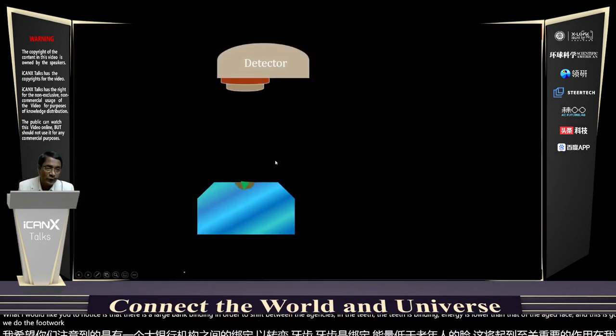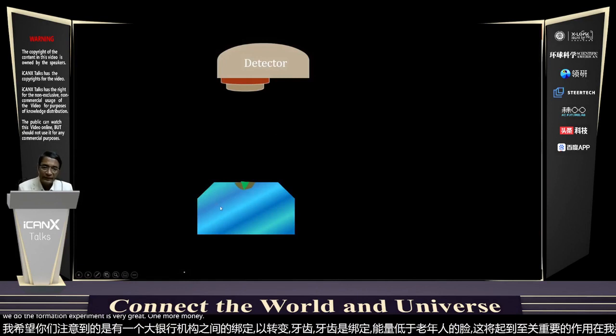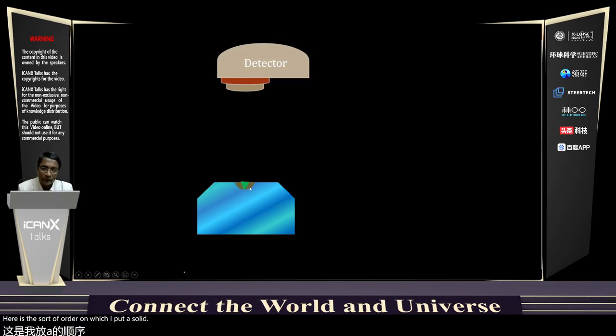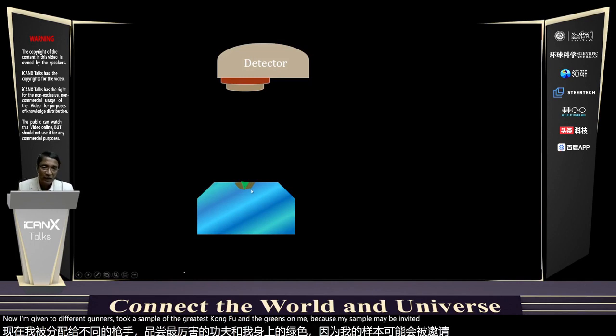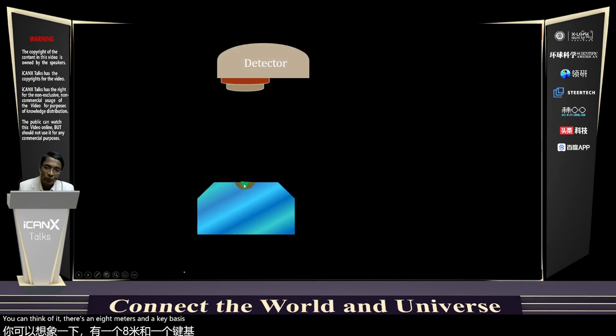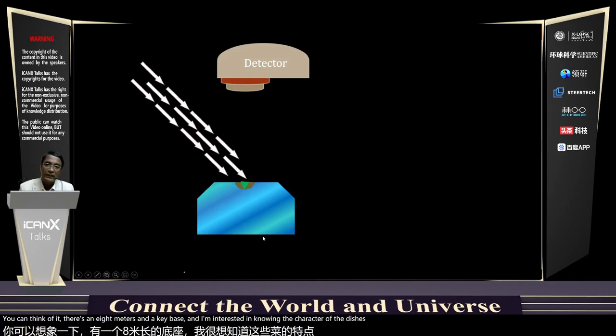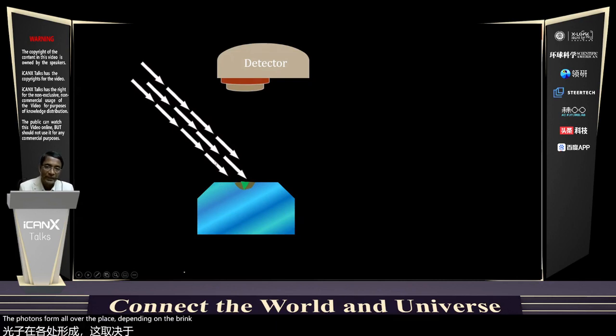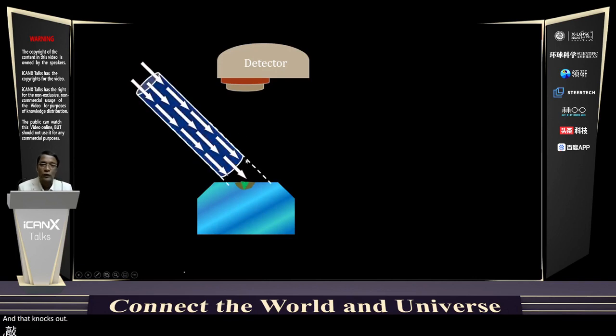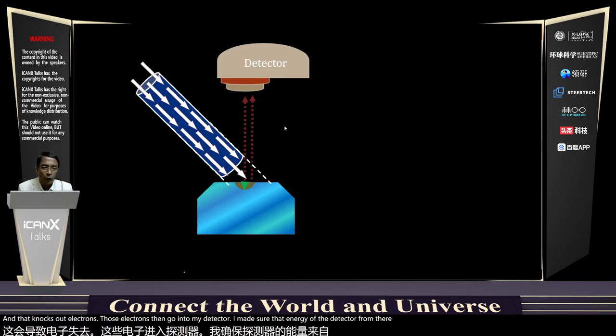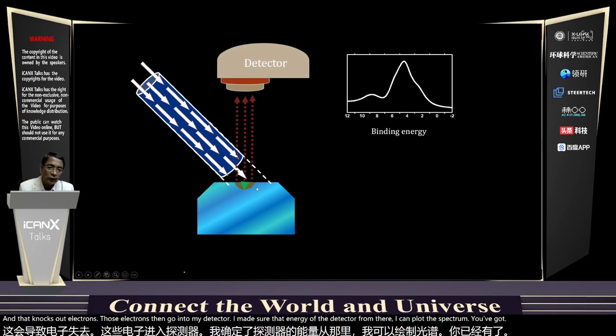How do we do the photoemission experiment? A very quick one. Normally, here is the sample holder on which I've put a sample. Now, I've given two different colors to the sample, the gray sample and the green sample, because my sample may be inhomogeneous. You can think of it, there's an H phase and a T phase, and I'm interested in knowing the character of the T phase. Normally, the way we do the photoemission, we bring in photons. The photons fall all over the place depending on the spread of the beam, and that knocks out electrons. These electrons then go into my detector. I measure the energy of the electrons. From there, I can plot the spectrum. If there's inhomogeneity, then I get signal coming from various places, and I get a very complex spectrum like this.